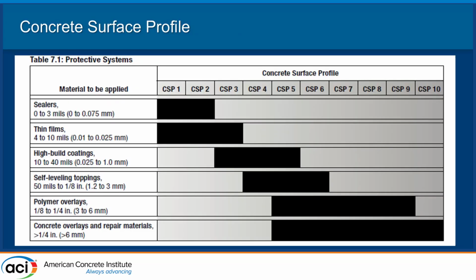So this is just a general guide, talking about the different coatings. Like I said earlier, the severity of the environment will dictate the degree of surface prep necessary. So if we put too much surface profile based on the thickness of the coating applied, there can also be problems there too. So as you can see on thin film sealers, a CSP 1 to 2 is a very, very thin, low profile. It's removed the latents, it's got us to a good sound surface, but it's not a really aggressive profile, which is what we want when we're talking about thin coatings.